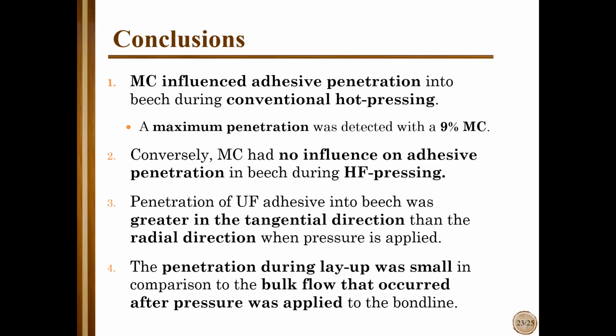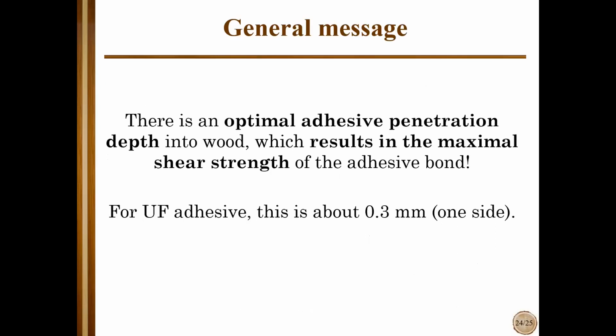However, there was no influence on adhesive penetration in the case of high frequency heating, because this is quite a different way of heating the adhesive. Then adhesive penetration was greater in the tangential direction compared to the radial direction. And last one, the pressure is actually the main driving force for adhesive penetration. So this also needs to be taken into consideration and controlled when we analyze adhesive penetration.